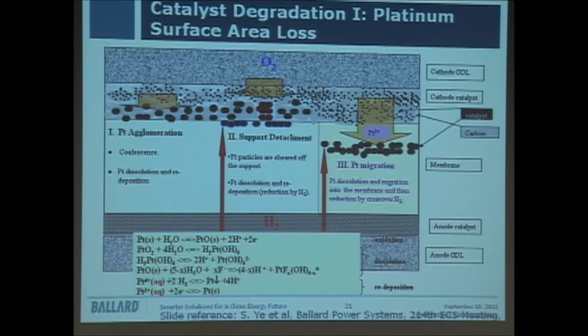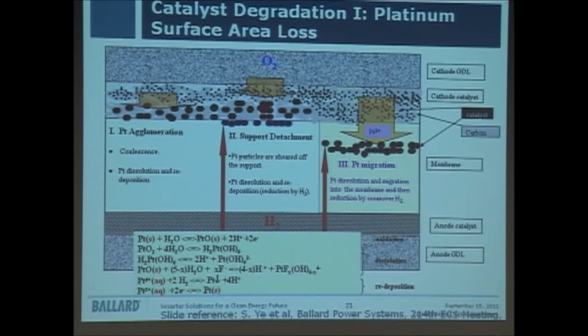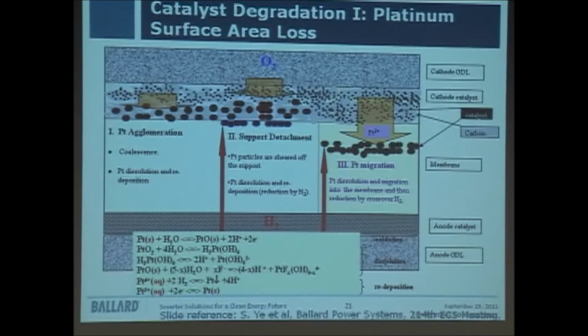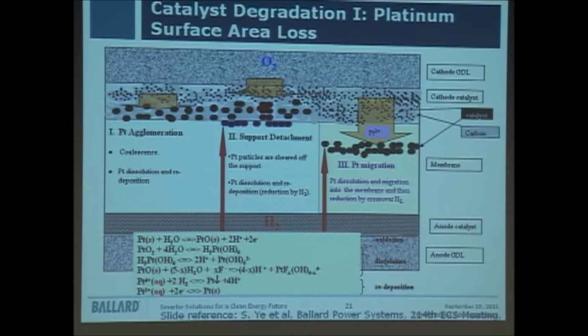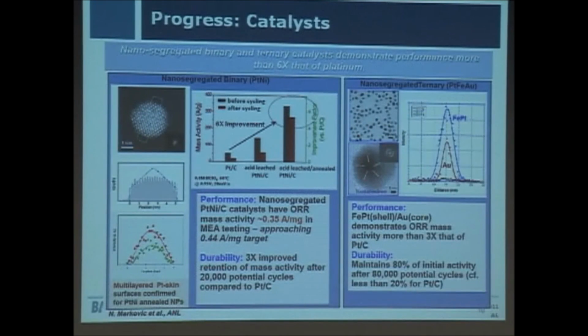The second one is that the platinum surface area itself will decrease during operation. As I mentioned before, catalyst is supposed to be the material that does not consume itself during the fuel cell reaction. However, in the fuel cell environment, they did consume themselves, because of the acidic environment, oxygen, and high potential. All of this makes the noble platinum catalyst become less noble, and then it will dissolve, oxidize, and migrate to the membrane. So they contribute to our overall performance degradation.